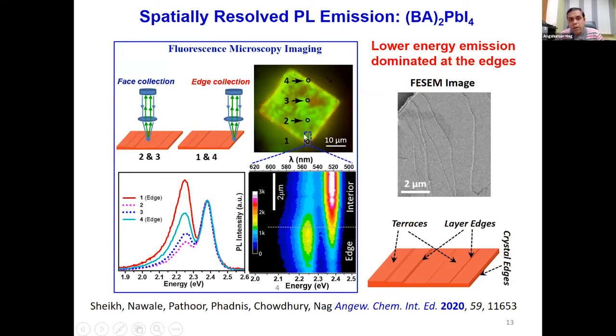This can be further probed by having the spatially resolved photoluminescence image for this small rectangular piece of the crystal. If you look here, when we are at the edges, the emission intensity for the lower energy emission is much higher, and as we go towards the interior of the crystal, the emission intensity of the higher energy peak increases. So it looks like the lower energy emission comes from the edges, but here you need to be careful, because when you look at the FESEM image of a piece of a single crystal, you can see the typical signature of a layered structure.